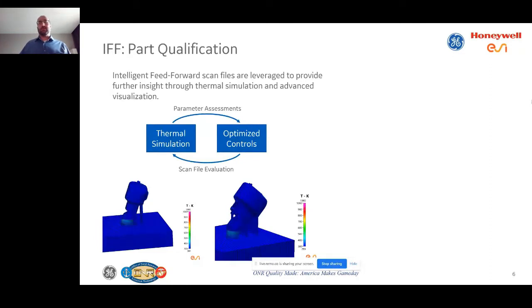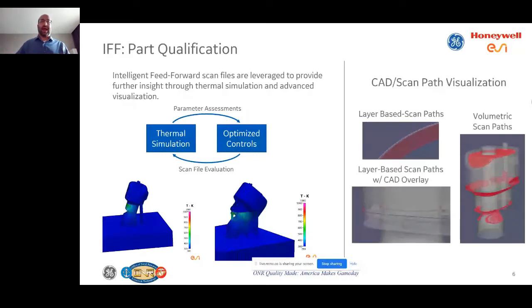But then taking a step further for intelligent feed forward control and this level of insight into the scan path control of an additive system, we can then furthermore illustrate how scan paths are being applied to a new geometry, inform the qualifying body of where and how feature sets are being flagged and identified through advanced visualization capabilities. Taking ourselves a step beyond what's typically seen for additive technologies, where you look at essentially a layer of the scan path at a time, which is shown on the slide here along the right.